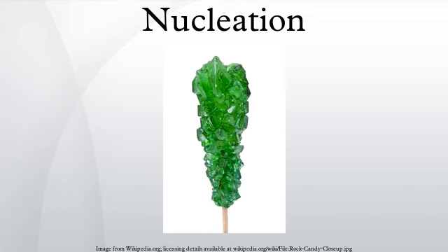The second factor in the expression for the rate is the dynamic part, which also has two parts. The first is the rate at which molecules add to the nucleus, increasing its size, and the second part is derived by assuming that near the top of the barrier the nucleus is effectively diffusing along the size axis, and so nuclei at the top of the barrier can grow diffusively into larger nuclei that will grow into a new phase, or they can lose molecules and shrink back to nothing. The probability that they go forward is Z.